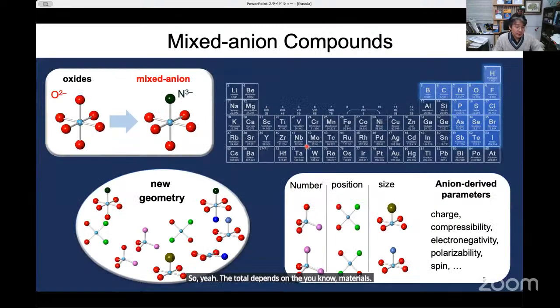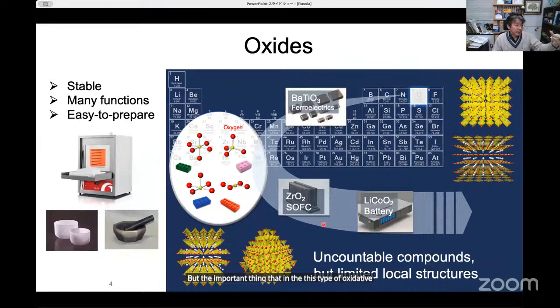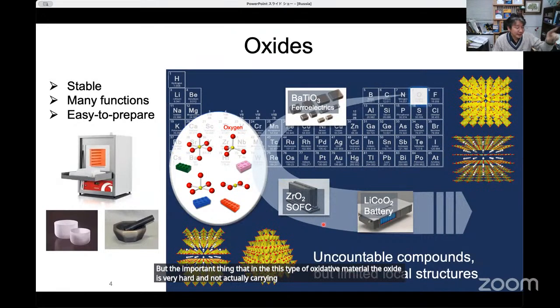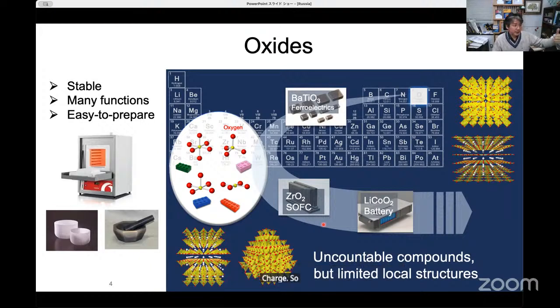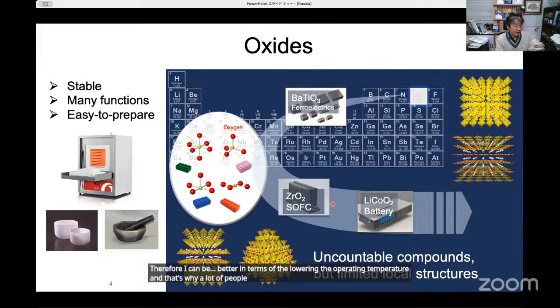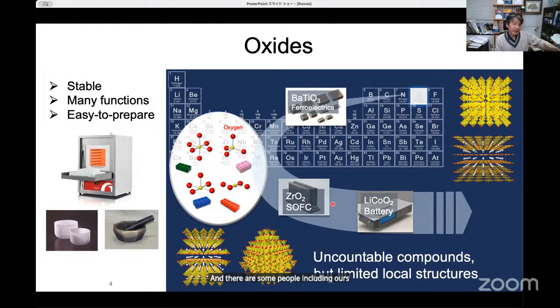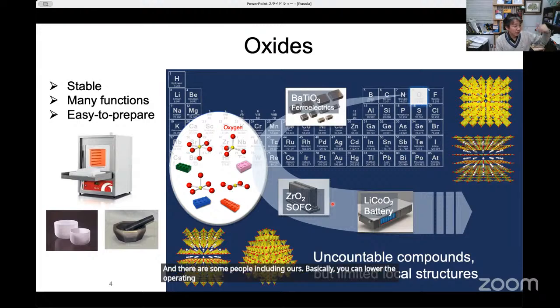materials. But the important thing is that in this type of oxide material, the oxide is very hard and carries 2 minus charge, so diffusion is more or less difficult. That's why the oxide ion conductors need higher temperature to activate. But in the case of oxyfluoride, if you are focused on the fluoride ion battery, the fluoride can be better in terms of lowering the operating temperature. That's why a lot of people are discussing or investigating anion-based ion conductors, such as hydride-based conductors or fluoride-based conductors. There are some papers, including ours. So basically, you can lower the operating temperature compared with the oxide materials. Is it okay? Okay, thank you very much.